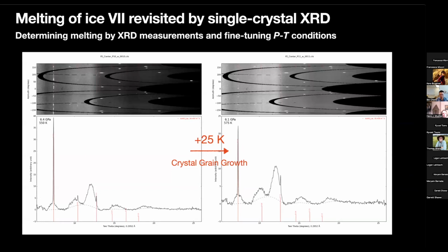So we utilize these newly developed techniques to determine the melting by XRD, for the samples loaded in the externally heated diamond cell, by fine-tuning the PT conditions. This is just an example that shows that at this temperature, 6.4 GPa and 550 Kelvin, we can see the diffraction peaks from ice.